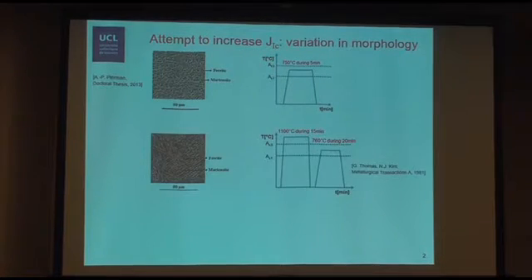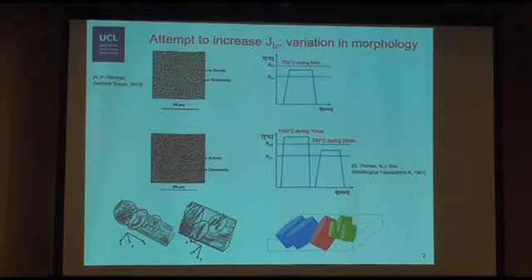However, it's possible to change the morphology of the martensite inclusions by applying a modified heat treatment with two steps. The first one in the full austenitic zone, followed by a second one in the intercritical zone. And that leads to a fibrous morphology. But as a first quick result, I've done a 3D microstructure characterization of such a steel using a serial section procedure. And it gave us information that the martensite inclusions aren't fibrous, as we thought looking at the microstructure in 2D, but rather lath-like platelets.